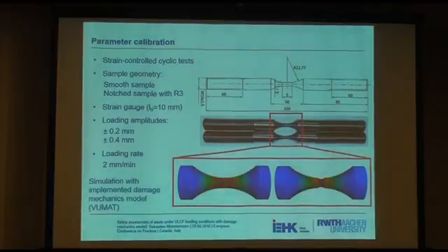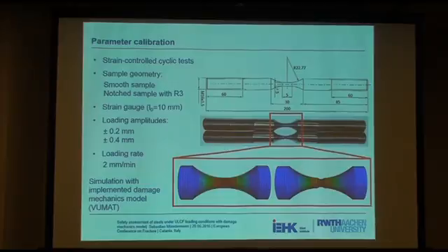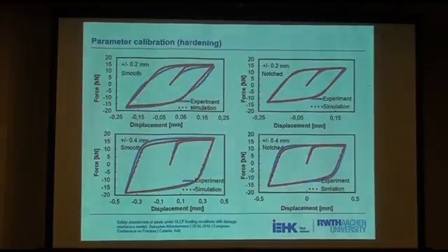Here you see the simulation models that we used. The element size is quite small, it's 0.15 millimeters. The model itself was implemented as a VUMAT for Abaqus. And here you see some results of our material parameter calibration.